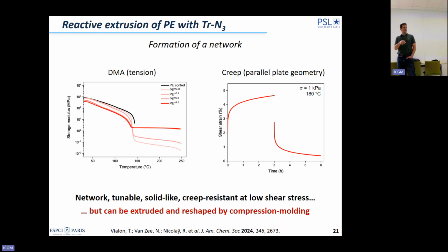stress, we see that the material, so this is the one crosslinking with 1 mole%, but 0.5 mole% is the same. We see that the material above the melting temperature of HDPE, so when it is molten, so when it is not crosslinked, it is a liquid, is behaving as an elastic solid. We have an instantaneous deformation, and then when we release the stress here, we recover all the deformation, if not